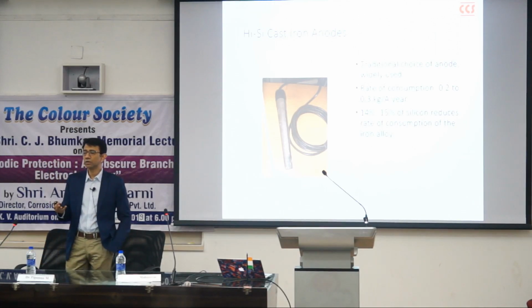A couple of slides on the types of anodes available. So this is what's called a high silicon cast iron anode. Basically it's iron. It has a certain element of silicon in it so as to reduce the rate of consumption. We know that the rate of consumption of steel or iron is about 9.1 kilograms per ampere year. By using 14 to 15% of silicon, we're able to reduce the rate of consumption to about 0.2 kilograms per ampere year. So this is a traditional impressed current anode used for the longest time through the 60s, 70s and